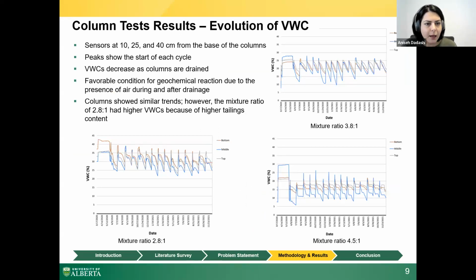These graphs show the evolution of volumetric water content for the commingled columns, the columns with 3 different mixture ratios. Sensors were at 10, 25, and 40 centimeters from the base of the column. Each peak shows the start of each cycle when we added water, and volumetric water content decreases as columns are drained.